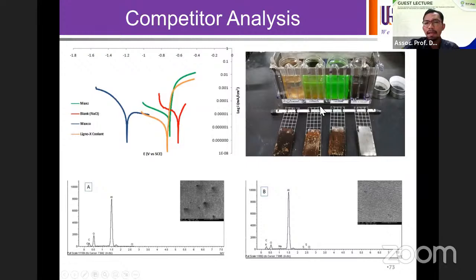So what we did was we incorporated modified lignin into the formulation, and we did some comparison with other commercial coolants. And from this dipping test, what you have seen is that after 3 months of dipping with the other types of coolant, the metal surface is very much corroded. But with our samples, there's no corrosion at all. Just a slight stain or slight localized corrosion that you will see. In fact, the electrochemical studies and also the surface studies showed that the formulated coolant that we have produced is even better than the commercial brand.